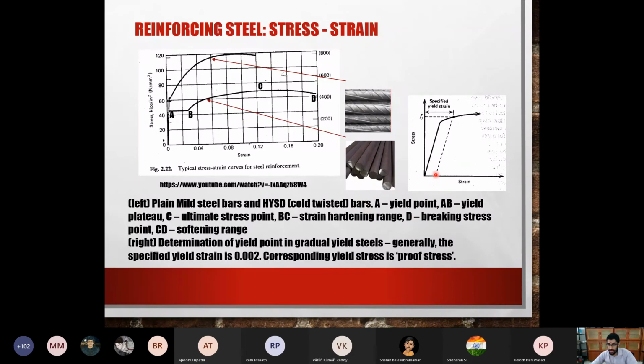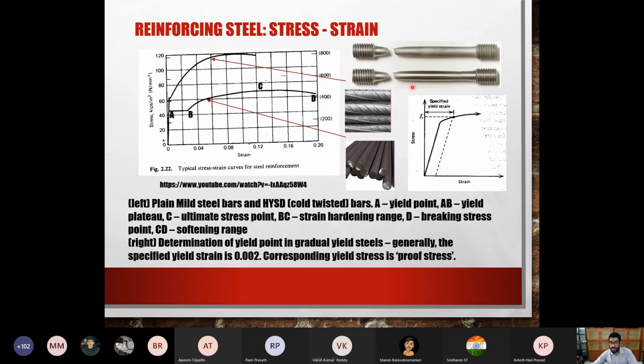So in that case, what you do is you just mark the point of 0.002 strain. You just mark the point, draw a line parallel to this initial line, and then make it touch the curve. Where it touches the curve becomes your proof stress. This is the way to find yield for high strength bars. This is just a broken rebar.